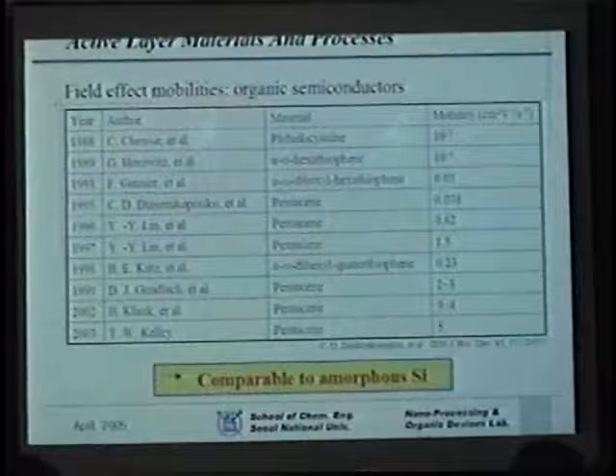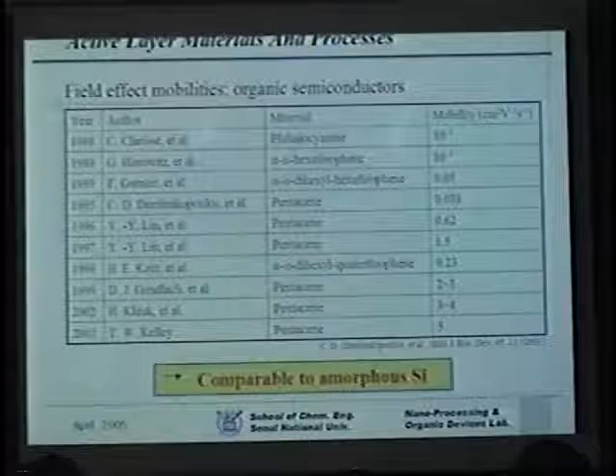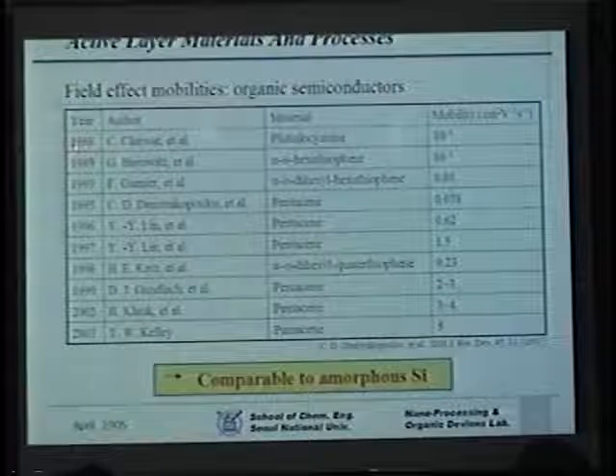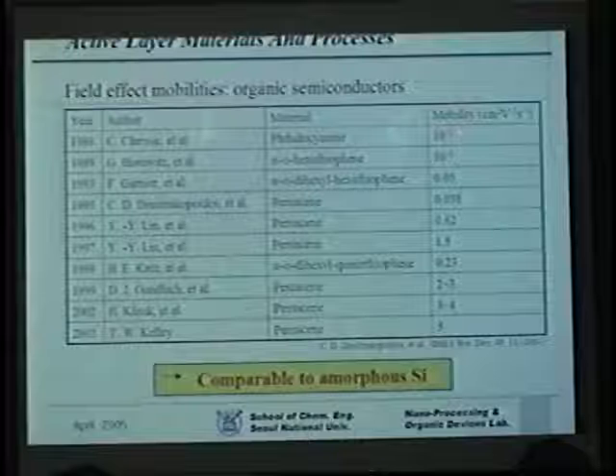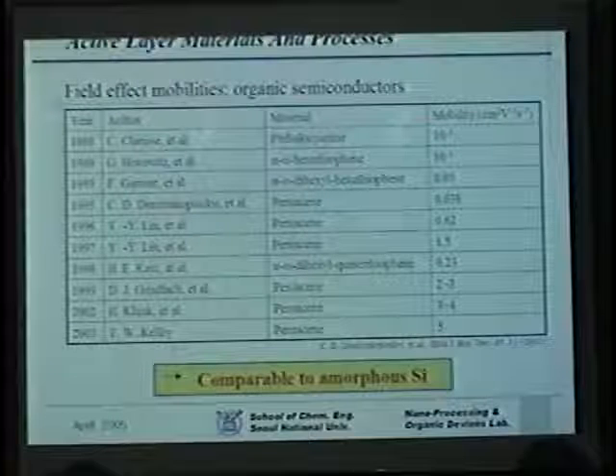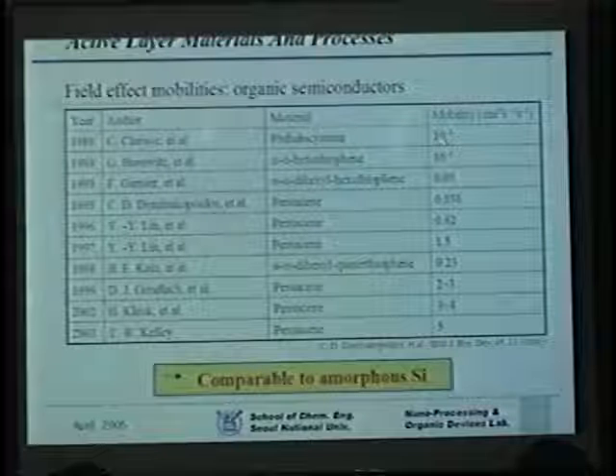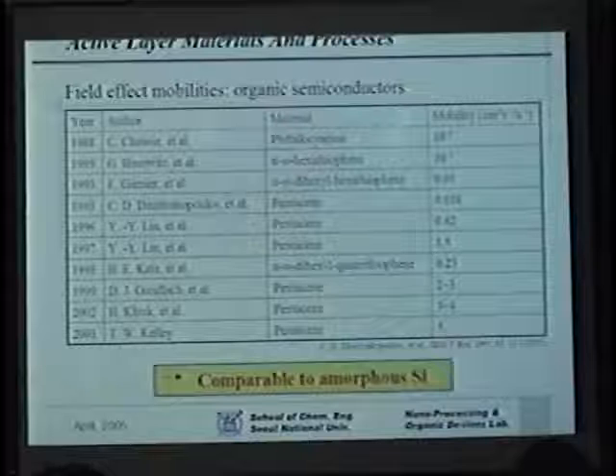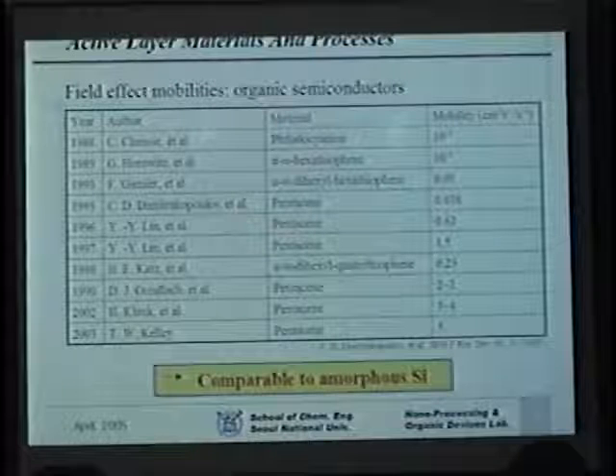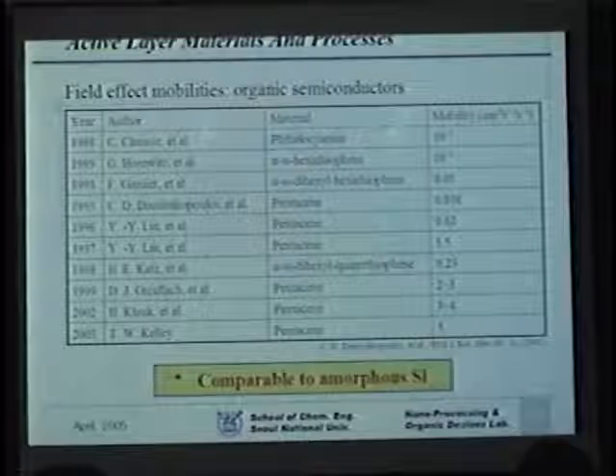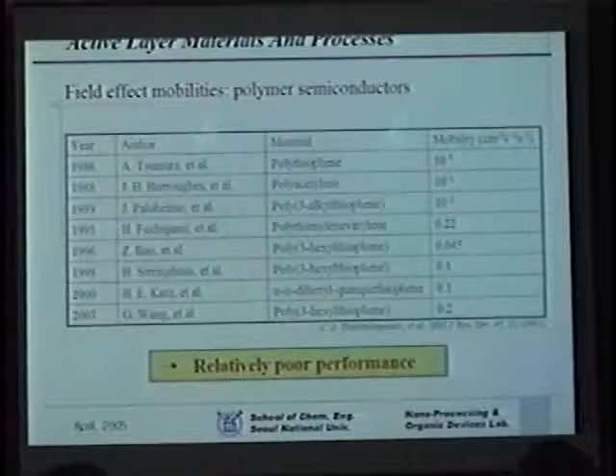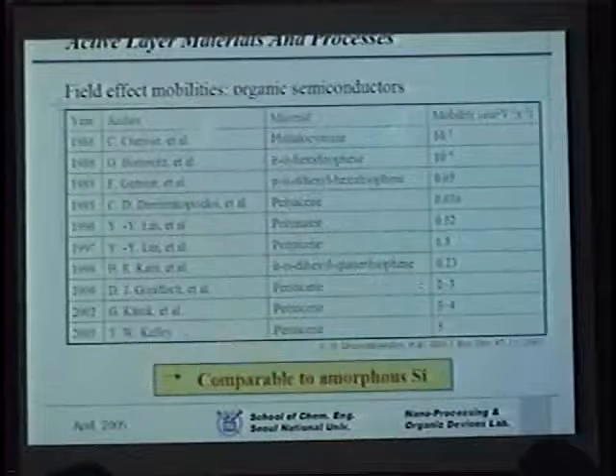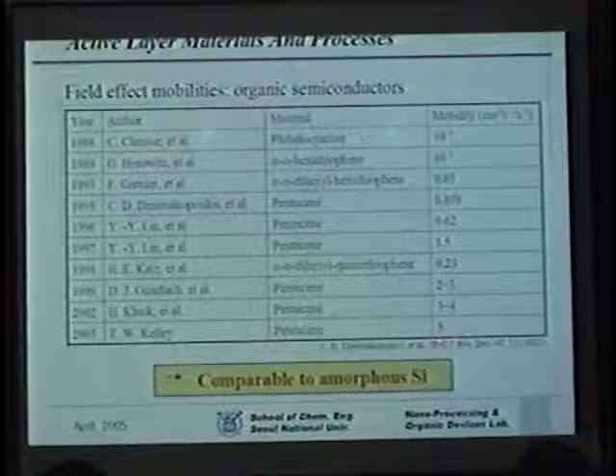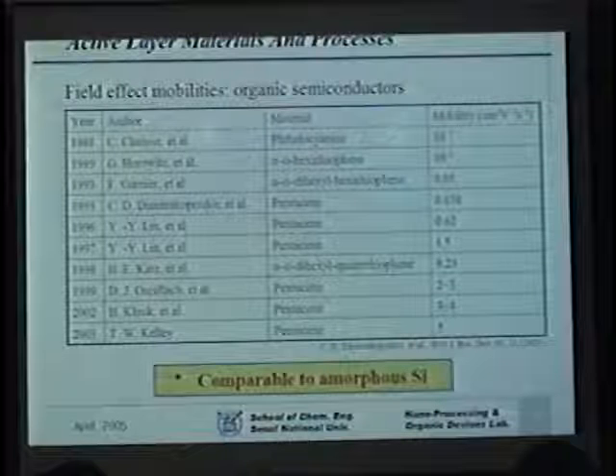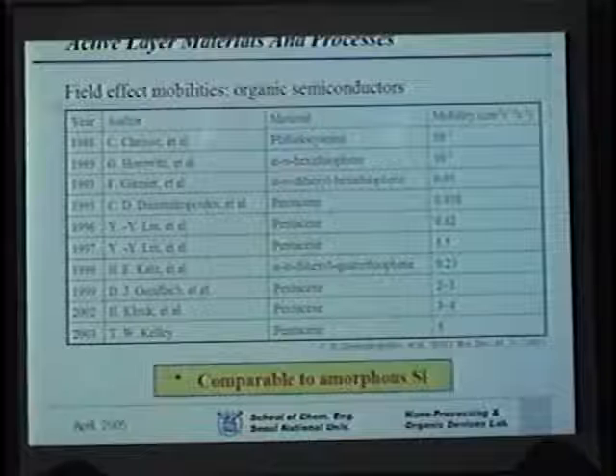So let's go back to field effect mobilities of organic semiconductors. It turns out that when they tried in 1988, the mobility was 10 to the minus 3 square centimeter per volt per second. And in about 15 years, there was about 4 orders of magnitude improvement in the mobility. These days, pentacene is about 5, it says. But if you are careful and willing to spend time, the mobility can go up to tens of square centimeter per volt per second. So the key to what is shown here is that in terms of mobility, organic transistor is comparable to amorphous silicon, and probably this is the key.